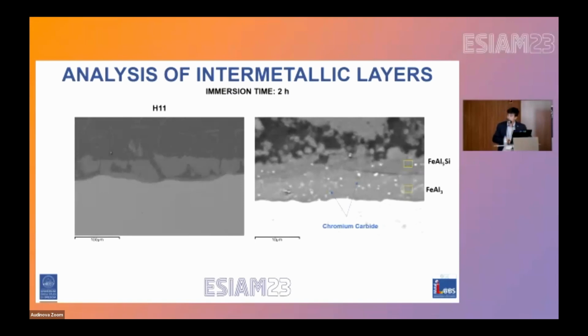Finally, here is presented the scanning electron microscope image of the cross-section of the H11 sample after 2 hours of immersion. Also in this case, the intermetallic layer is mainly composed of 2 different phases. In this case, as can be noted, the chromium carbide particles are well embedded also in the intermetallic layer, which, according to the literature, provides a sort of physical barrier to the diffusion of iron and aluminum atoms, and determines the highest corrosion resistance of the H11 samples.